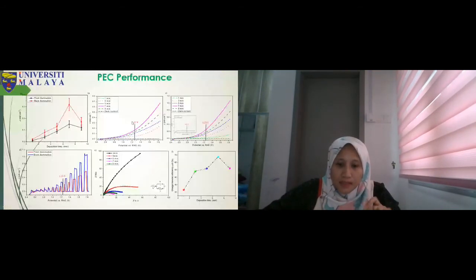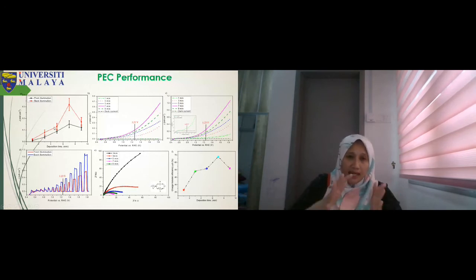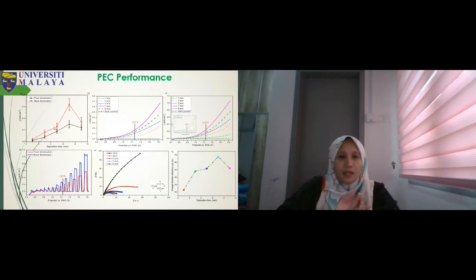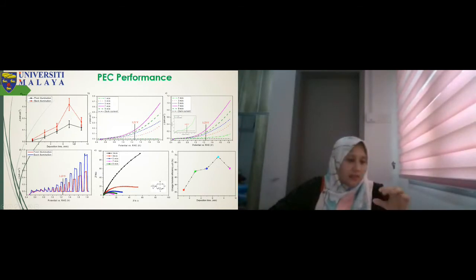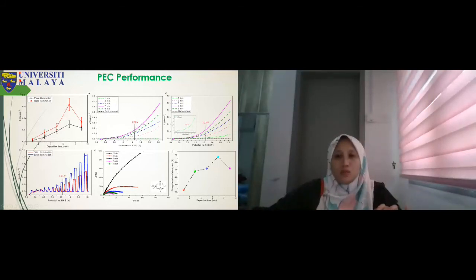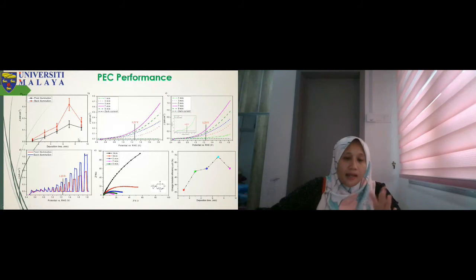Okay, this is for the PEC performance. For the PEC performance, I want to stress that we did the analysis for the back and front illuminations. The finding is that the back illumination has a higher photocurrent density compared to the front illumination because it is easier for the hole diffusion than the electron diffusion. So this is the standard deviation, which means the samples were done in triplicate. This is the potential versus RHE in volts, at 1.23 volt, and it shows that the back illumination is the highest at around 0.32 milliampere. This one is a chopping measurement, to prove that our photoanode is active under visible light, under light and under dark.